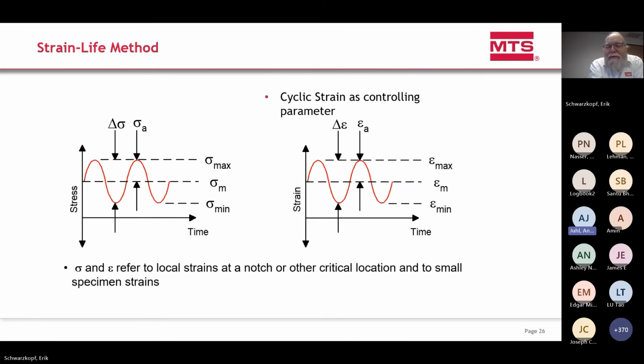an initial size or a strain minimum value to cycle it again. Usually, these strain amplitudes result in compressive loading, even if the two strain amplitudes are positive. So that graph on the right could easily have a tension stress and a compressive stress, even though all the strains are tension.